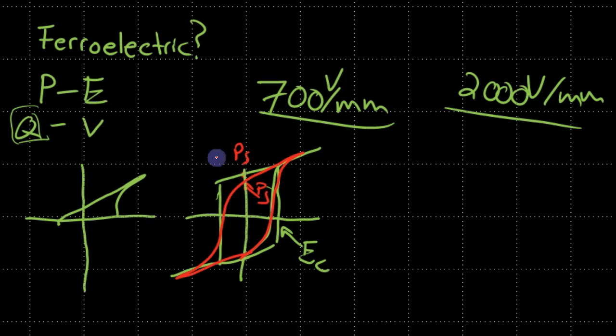The spontaneous polarization I'm mentioning is not exactly equal to the actual spontaneous polarization of the material, but it's very close. The reason is that even with a very large applied electric field, not all domains can physically change direction into the single-domain state. For a single crystal material this is possible, however for a polycrystalline material it largely happens but doesn't happen completely.